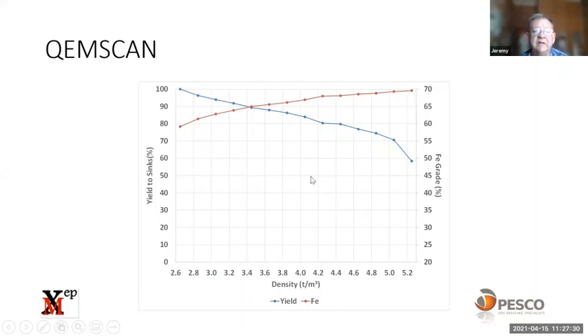Here's the yield and the Fe. So you can see the yield drops down. For example, if you could cut it at 4, your yield would be about 85 and your grade would be about 66. So you can see this sample is actually very well liberated. The feed grade was just below 60, and you could generate up to almost pure, there are some pure minerals or particles of hematite in there.